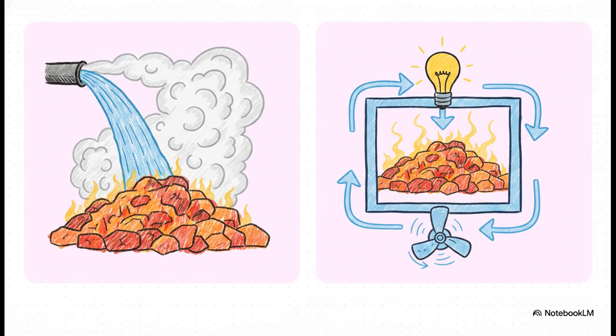Finally, after maybe 12 to 24 hours of baking, this glowing, red-hot carbon skeleton is physically pushed out of the oven in less than a minute. And it absolutely must be rapidly cooled, or quenched, before the open air turns all that hard work into a literal pile of ash. Now, historically, engineers used conventional wet quenching, just blasting it with over 1,100 liters of water per ton, creating this massive cloud of steam. But modern facilities, they use coke dry quenching.